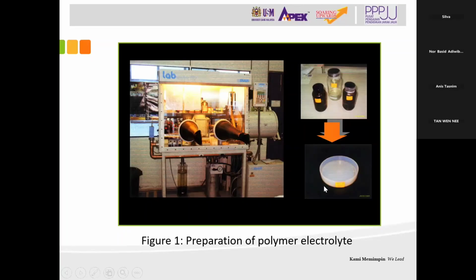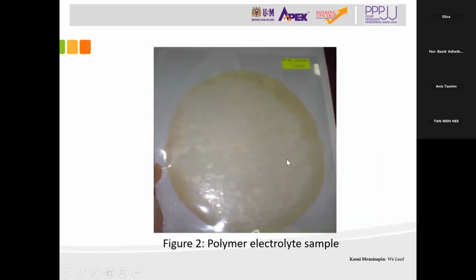And then the film. This is the sample of film that we have, the ENR50 based polymer electrolyte sample after we do the work. The film is deposited after evaporation, further dried in the vacuum oven, and after that we characterize it. All the experimental work is conducted in the glove box because the polymer electrolyte is very sensitive to humidity and oxygen.